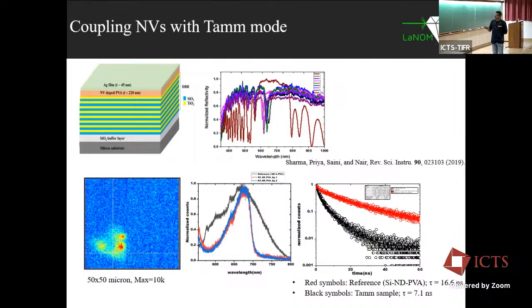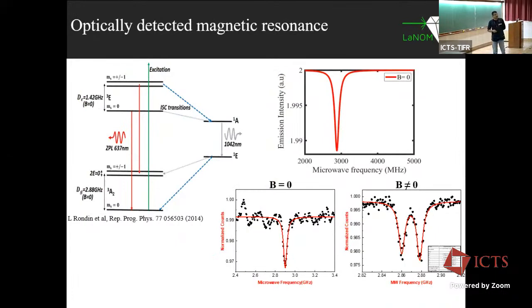And we mount the sample in our confocal, and we got some bright NVs coupled with the TAM. The black line is the reference measurement from the reference sample. And when we have a TAM structure, you can see that it tries to peak around 660 nanometer. That's where the cavity is designed. So you can suppress the phonon sideband here and here, and only try to excite the mode very close to where your cavity mode is designed. And the most important measurement is the decay rate. The reference is slow, but the sample shows very fast emission of light. And once you have a single NV center, we can have bright single photon emission, because the NVs in a medium emit, let's say, with 30 nanosecond lifetime, we can come down to around 7 nanosecond lifetime using cavity coupled structures. So this is something which Fani talked about in detail in the previous slide.